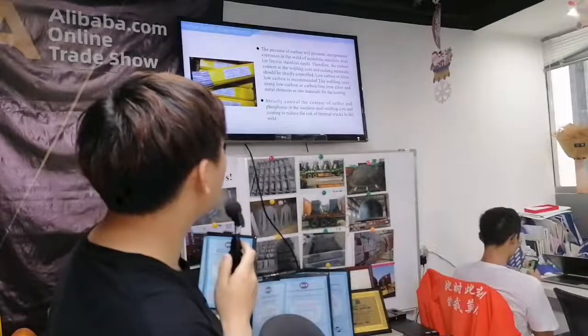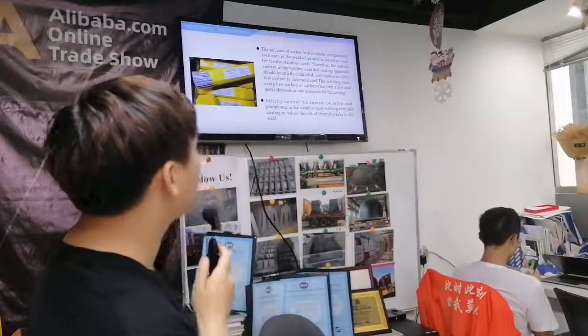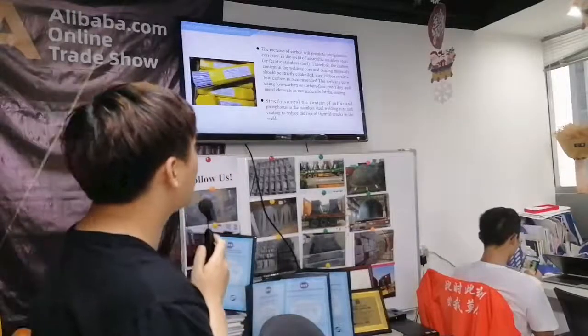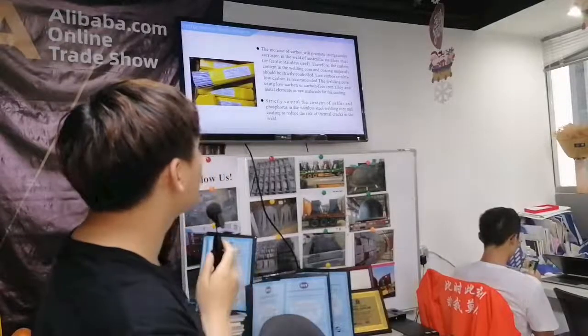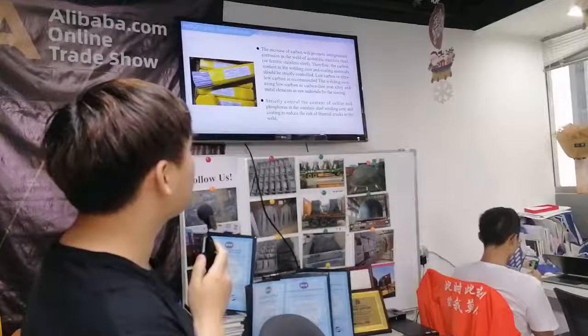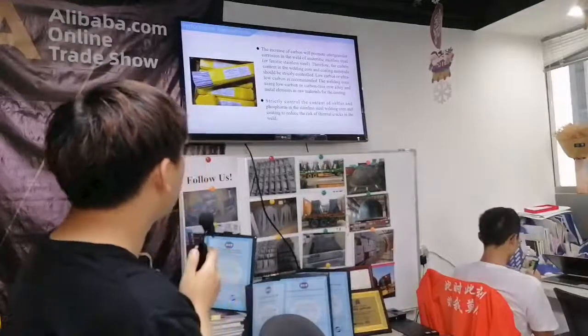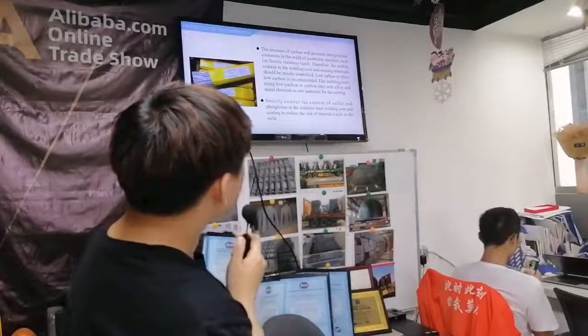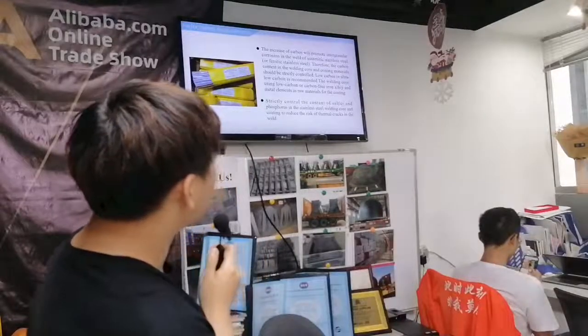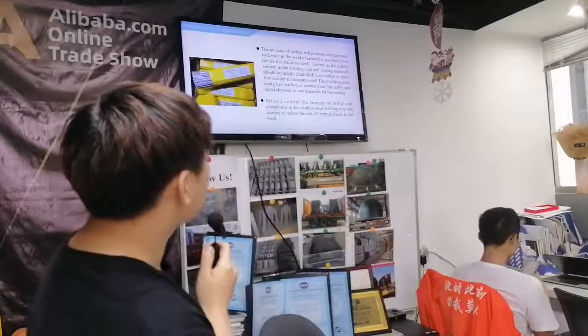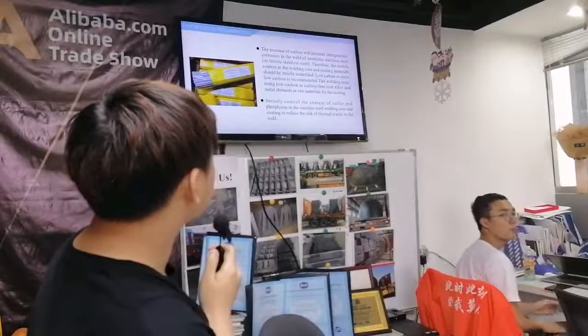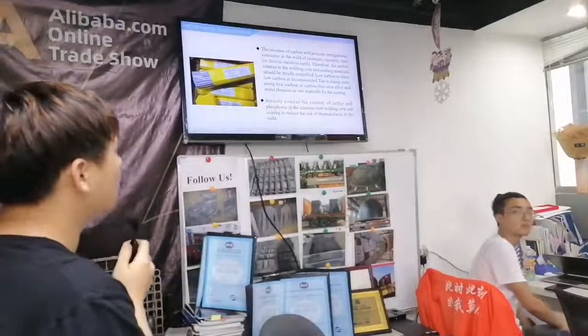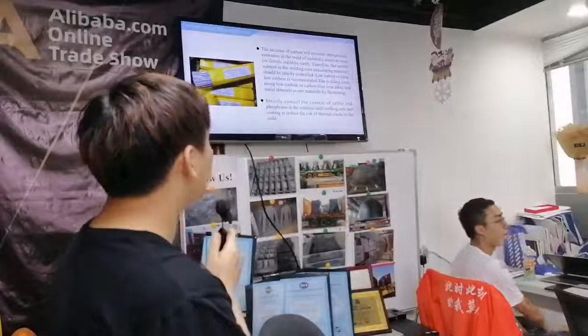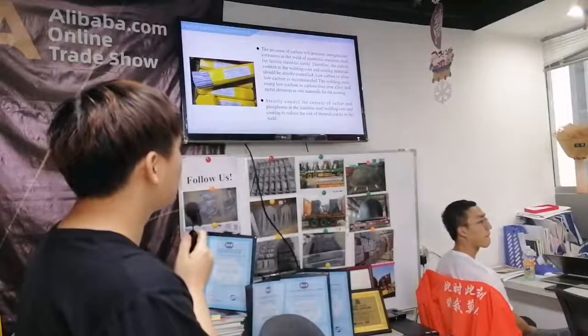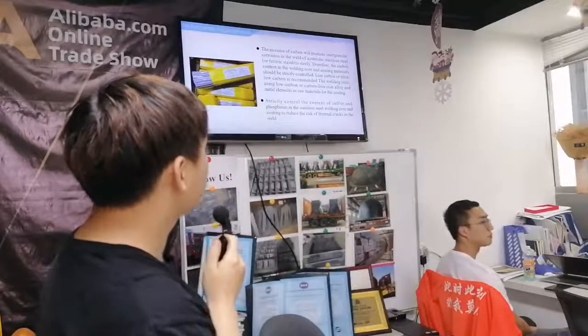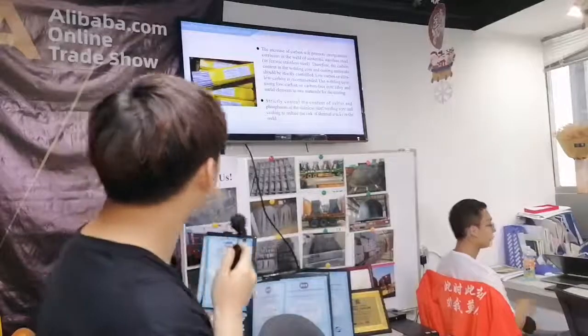The welding core uses low carbon or carbon-free alloy and metal elements as raw materials for the coating. Strictly control the content of sulfur and phosphorus in the stainless steel welding core and coating to reduce the risk of thermal cracks in the weld.